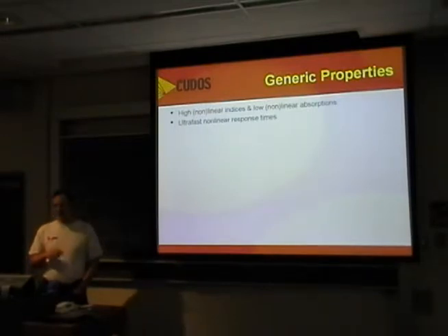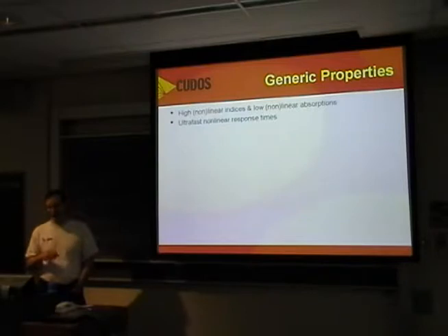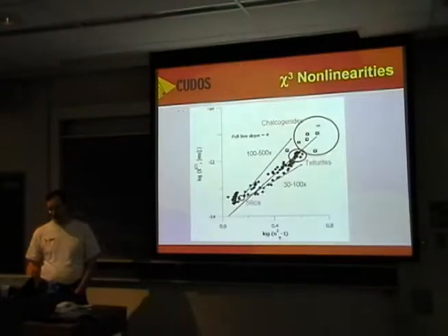So these materials have quite a lot of interesting properties, and I'm just going to touch on some of those now. First of all, they have both high linear and non-linear indices, and low linear and non-linear absorptions, which we've seen is actually quite important. Because they're glasses, because it's an electronic process, they have ultra-fast response times as well.